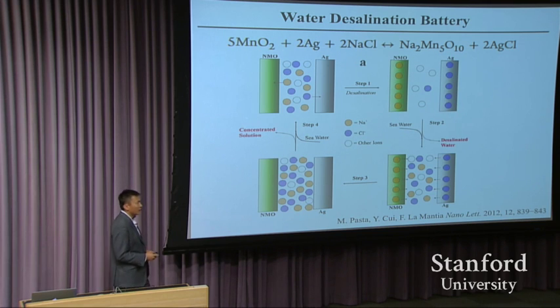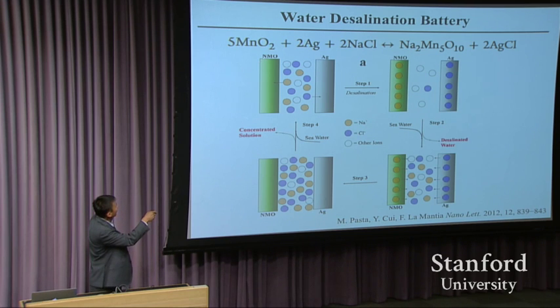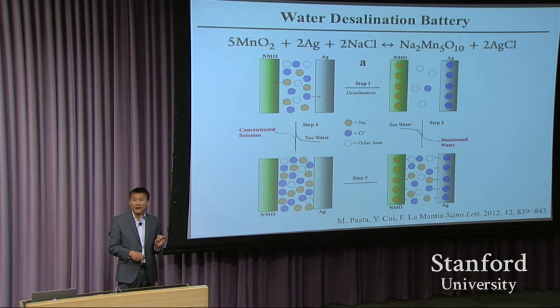So we construct a new device. We call this a water desalination battery. So we take NMO, that's sodium manganese oxide, and silver. And then you do the battery discharge. This is the seawater right here as an electrolyte. You discharge the battery. Sodium will go into the manganese oxide. Chlorine will combine with silver, generating silver chloride. So by the schematic drawing, you see the lower concentration now. Each of those balls right there indicates ions. You're now taking away the salt from the seawater. So you get the fresh water. You flush this fresh water out.